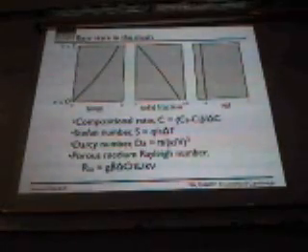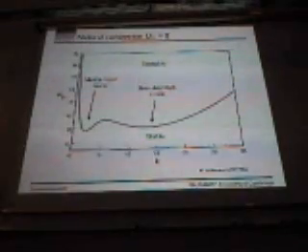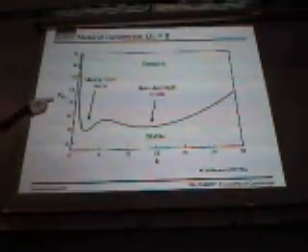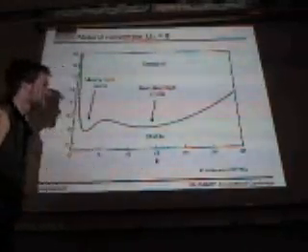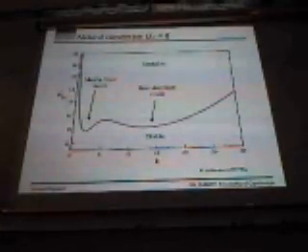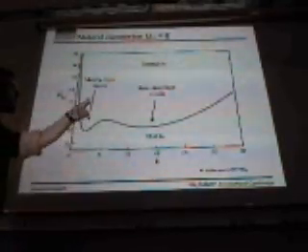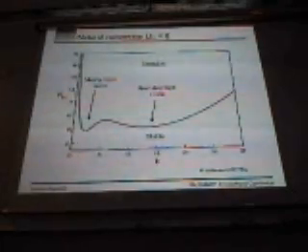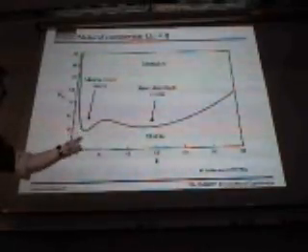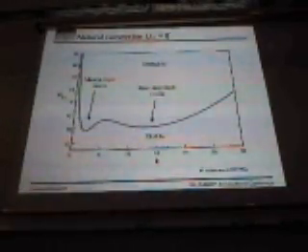So doing the next step in this kind of system of PDEs, you get the following linear stability analysis. Here I've plotted the porous medium Rayleigh number versus wavelength, doing a typical linear stability analysis. This was first done by Worster in 1992. And as is typical, this is the neutral stability curve separating stable regions from ones which are unstable. And you find that there are two modes of convection in this system. One is this long wavelength, small wave number, mushy layer mode. And one is a small wavelength, large wave number, boundary layer mode.